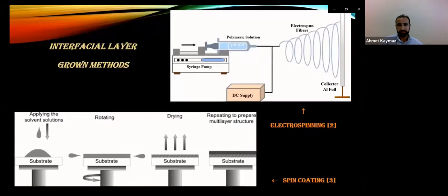Oxide, insulator, organic, or ferroelectric layers can be grown as an interfacial layer between the metal and the semiconductor materials by a natural or deposit method. There are many methods used to deposit the interfacial layer, such as spin coating, electrospinning, and sol gel techniques. Some of these methods can be seen in the figures. Consequently, we didn't grow any interfacial layer for this sample, but it can be said that there is a natural oxide layer between the metal and the semiconductor materials.